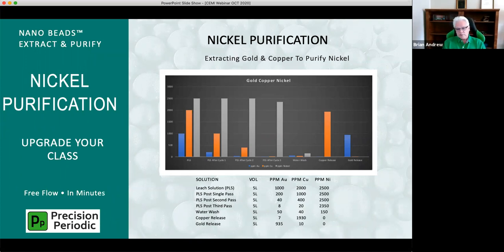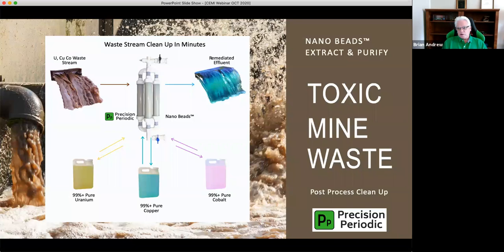So the PLS comes into the filter system, comes out the bottom of the filter system in minutes, and then we pull out the gold and copper, giving you a class one nickel and also two other marketable products in the form of copper and gold. And so in one cleanup process, we produce three marketable products. Clearly the nickel is the most value in this case because it's huge, but the gold and copper add to the income.